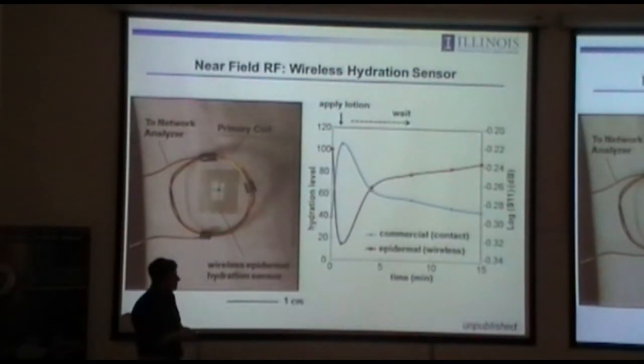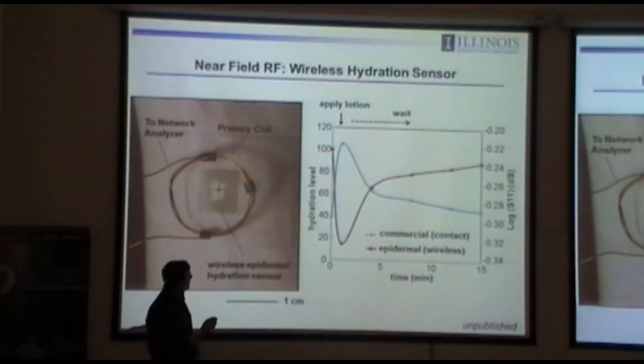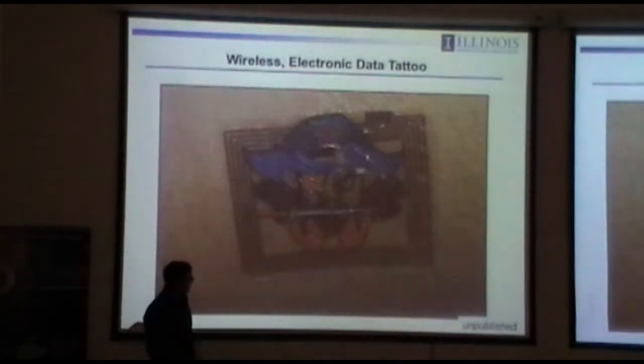A lot of the stuff you'd like to be able to do purely wirelessly, you can do by inductive coupling. This is one example. We have an impedance electrode pair here. We can measure galvanic response of the skin, conductivity of the skin, just by looking at mutual inductance coupling between a primary coil here and a secondary coil that's built into this epidermal format and laminated onto the skin. And we can look at the effects of applying moisture to the skin. This is an epidermal wireless measurement of S11 from the mutual inductance. And if you compare with a commercial contact moisture meter, you see a very good correlation between these two types of measurements. And wireless is really where you want to go.